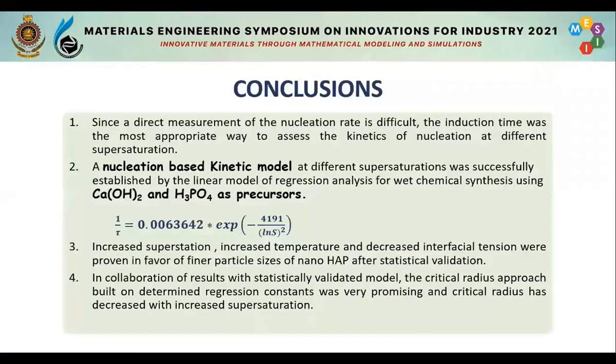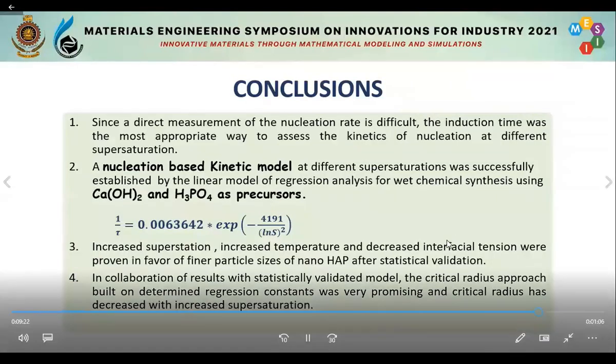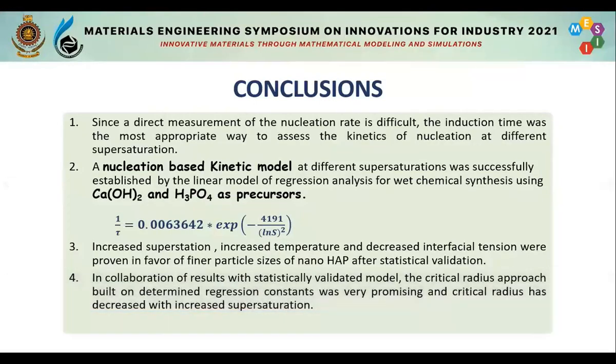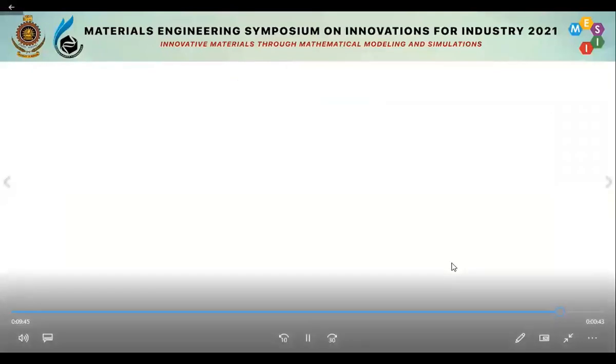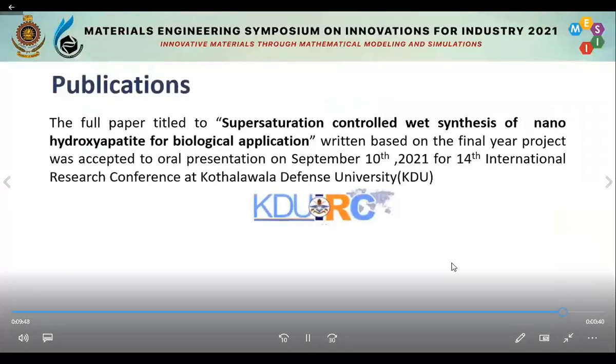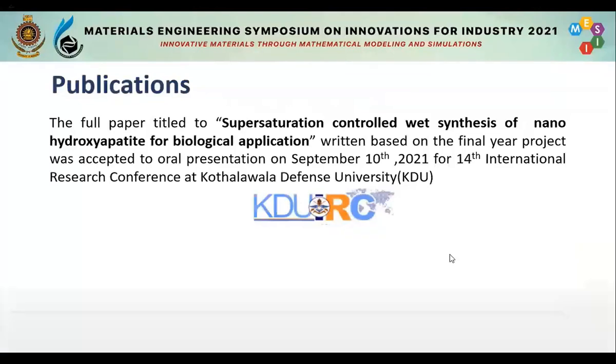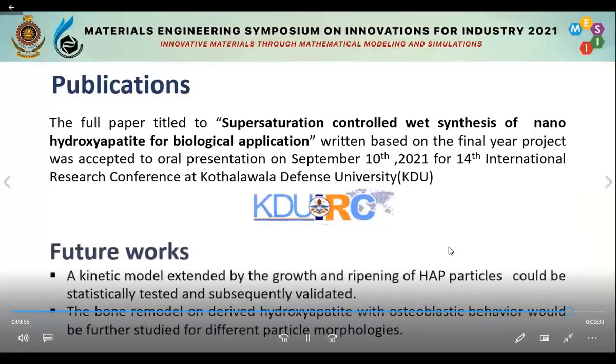In the conclusion, we can conclude that direct measurement is not possible for the nucleation rate, so induction time is a good alternative. Then we can derive this relationship, and we can use it for modeling purposes. Increased supersaturation, increased temperature and decreased interfacial tension were proven to favor finer particle sizes. Finally, in correlation of results with the statistically validated model, the critical radius approach was well suited for explanation purposes. Finally, we did a publication under the KDU 14th International Research Conference with the same title, and some future work is there with